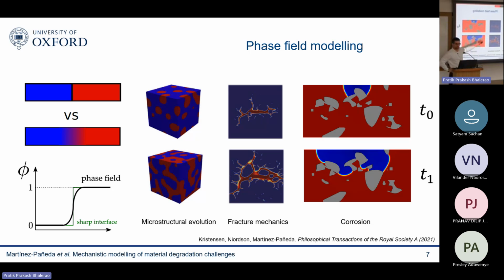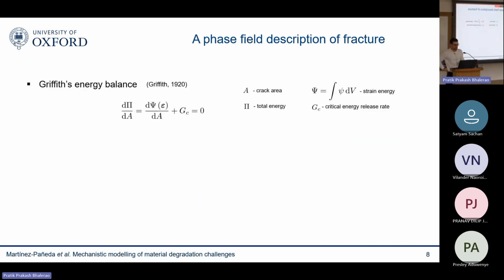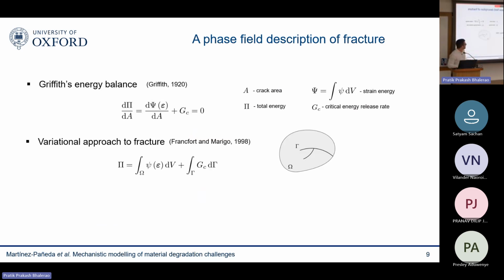So the nice colors that you see in your computer agree with experiments, agree with reality. And this is because phase field provides a platform for Griffith's energy balance. So everything is based on the thermodynamics of fracture. Those of you who have seen fracture mechanics will remember that Griffith, one of the fathers of the field, postulated that in order for fracture to be consistent with thermodynamics, for a crack to grow, the energy stored in the material had to be equal or larger than the fracture energy, the energy required to create two new surfaces. And you can postulate that energy balance in a variational form.